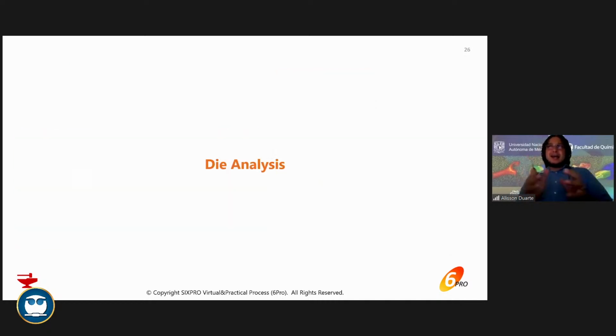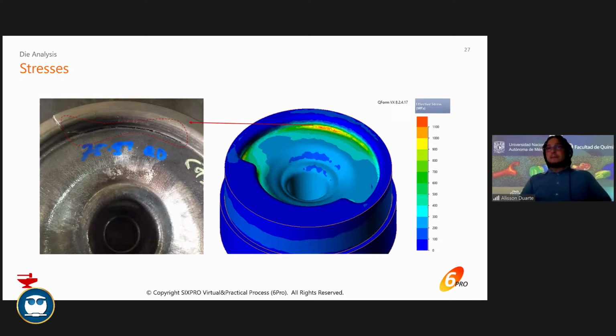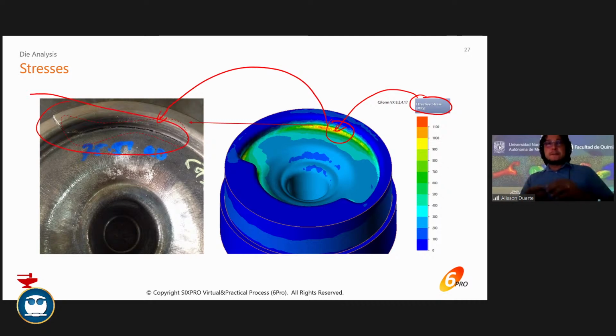All right. I showed you a little bit about defects in forging, now about die analysis. For example, this is a die, it's a bottom die. You can see that I can check first of all the effective stress. You're going to see that I have very big or high effective stresses here, that they are coincident to the areas in the die that will break. So the first very important result we have to check in the die is the effective stress. Because if the effective stresses are too high, it means it's getting closer to the yield stress of the material of the die. So it's important that we analyze it, you know.